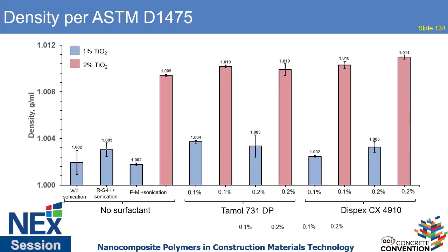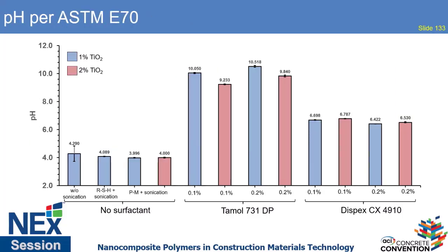Density per D1475 was also measured, and this is also just a checkpoint, a lot of times for us to make sure that there are no issues. So you have theoretical points, and this is just an actual measure to show. And as we expected, the density for the 2% suspension or dispersion is higher than the 1%.